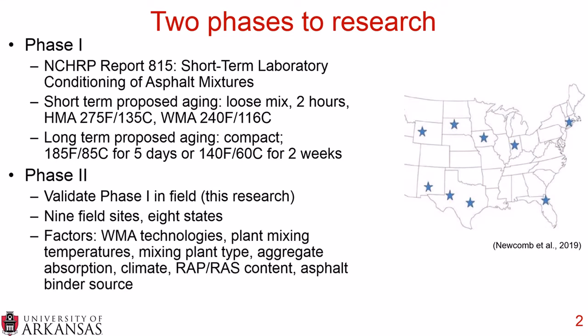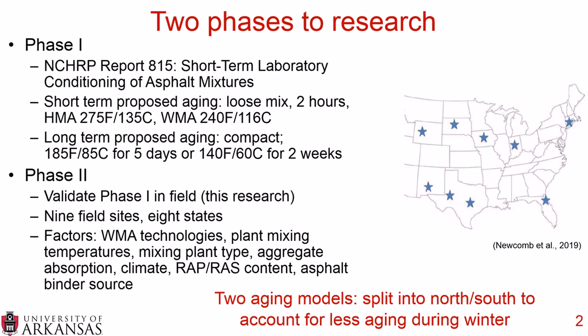The different factors they looked at were warm mix asphalt technologies, plant mixing temperatures, the mixing plant type, the amount of absorption of the base aggregate, the climate, the RAP and the RAS content, reclaimed asphalt pavement and recycled asphalt shingle content, and then also the asphalt binder source. They also looked at the 2 aging models, which they had split into a north and a south region. So the 5 stars in the northern portion of the map were in the north region and the 4 in the south region, to account for the less aging that occurred in the colder northern climates in the United States.